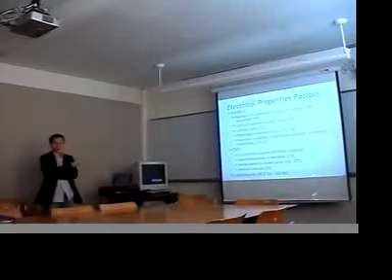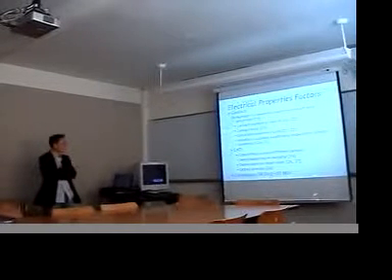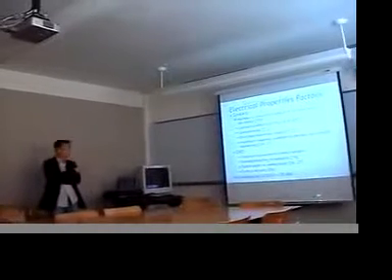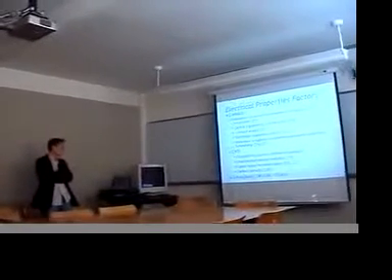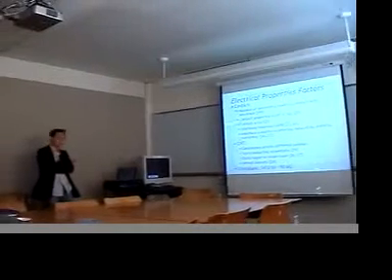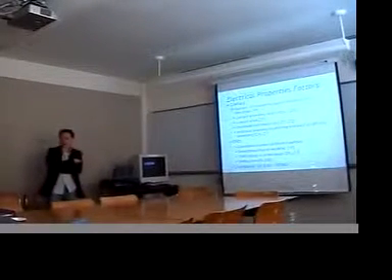CNT, like I said before, each CNT might be very different even though you grow them under the same condition. The CNT can be both semiconducting and metallic, so you need to make an intelligent guess of what it is. There's also a dispute about outer layer and inner layer, which one contributes more, and defect density also plays a part. So what it all comes down to is that there's a very wide range of reported values, and these are all single wall, single carbon nanotube connections.